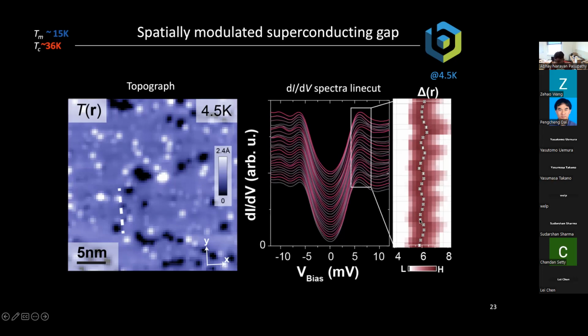And the period of this modulation is about 8 lattice constants along one of the principal axes of the crystal. Now, you can visualize this much better by doing the following. You pick a particular energy. So we pick this particular energy, which is the energy of the coherence peak. And I plot the density of states at this particular energy everywhere in space. We call that a conductance map.